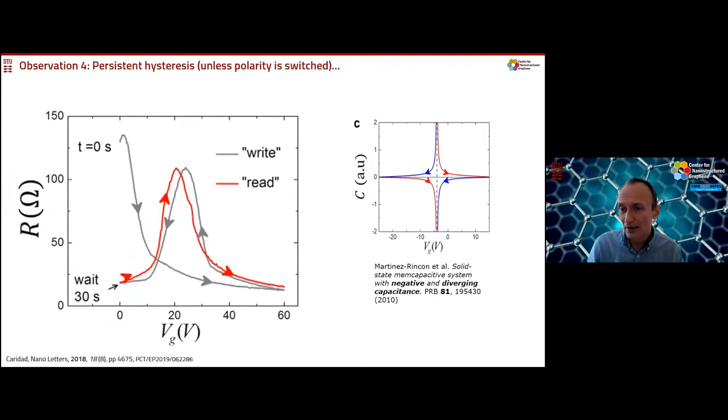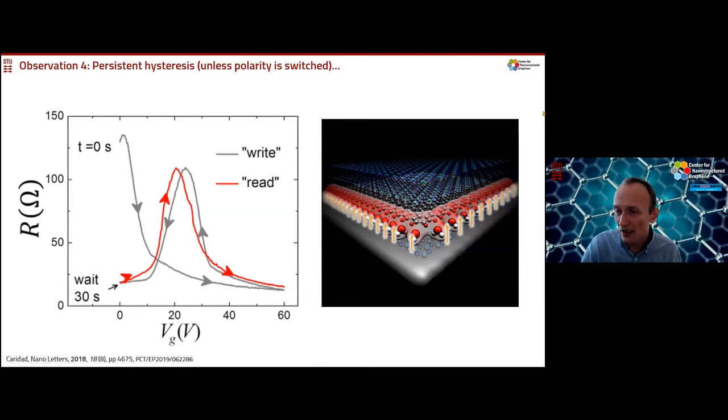We don't know how fast these water molecules flip, but we are pretty sure that this picture is at least partially correct. Here is the boron nitride, and you see the graphene below here. At the edge, we can orchestrate that the water molecules align in the same direction and stay like that for a while, and flip them to the other side at will. This only happens when we have oxygen at the edges, and it only happens when we have a sufficiently large dipole moment of the molecule.